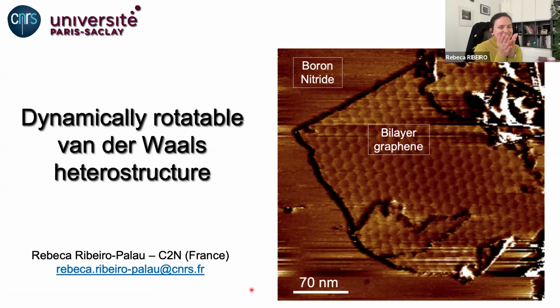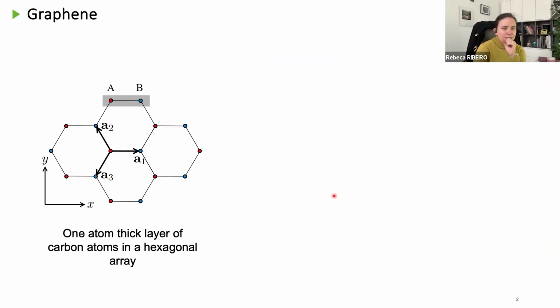What you are seeing here in the first slide is one of my favorite AFM images. This is a piece of bilayer graphene deposited on top of boron nitride. And you can see these hexagonal patterns that form on top of it. In fact, this is a moiré superlattice. We're going to see what a moiré superlattice is, but just so you know, this is the consequence of the alignment between the 2 layers. So let's just start with the basics, okay?